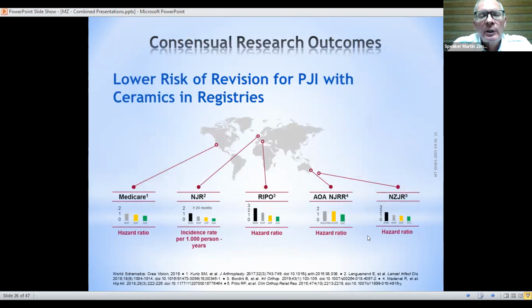Actually, this study is not the only one showing this kind of results. If you look at different important registries worldwide, the Medicare registry from the USA, the NJR, which was just shown now, but also the Italian registry, RIPO from Emilia-Romagna, the Australian registry, as well as the New Zealand registry, all of them clearly demonstrate that there is a consensus: by avoiding the usage of metallic components in the bearing, typically cobalt chrome, and by using ceramic, you are reducing the risk of having periprosthetic joint infection.